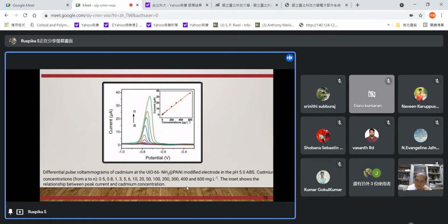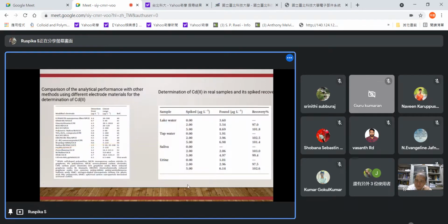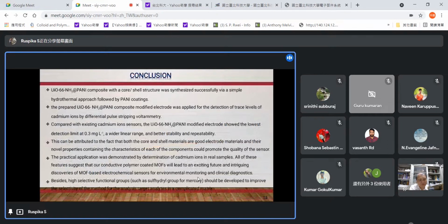And this is the DPV curves at different concentrations. And these are the comparison table for different electrodes for the determination of cadmium with the other modified electrodes. The feasibility of the proposed sensor was validated by analyzing cadmium in lake water, tap water, saliva, and urine, which is shown in this table, and which shows recoveries of 97 to 103 percent. In conclusion, the composite was successfully prepared via hydrothermal method,